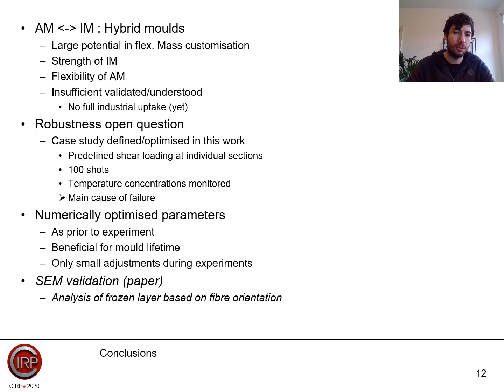Finally, our conclusions of this work. Injection molding with additive manufactured plastic molds has a large potential in the context of flexible mass customization, as it can combine the strengths of the conventional injection molding in terms of production throughput with the flexibility of additive manufacturing techniques. Most commonly, plastic inserts for steel molds are produced, yielding hybrid molds. However, the thermo-mechanical behavior and the functional lifetime of these mold inserts is insufficiently understood in literature to allow for full industrial uptake.